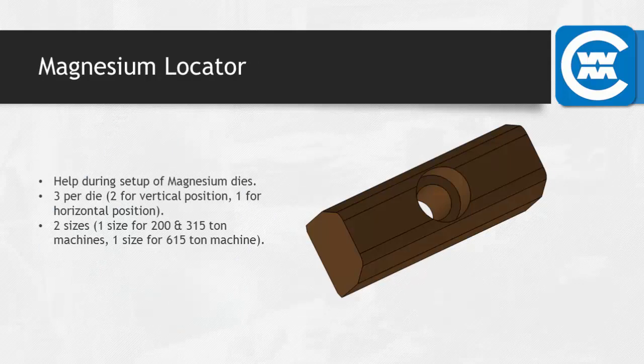the platen and is then installed into the die, so that automatically aligns your die to the cover half platen, and then you can clamp both halves together. Magnesium doesn't allow for that contact on the nozzle to be used as a location position. So we have to actually install these locators on all of our magnesium tools, and they fit into the same clamping slots that are already in the platen. This is how we align any hot chamber tool, whether it's magnesium or zinc.